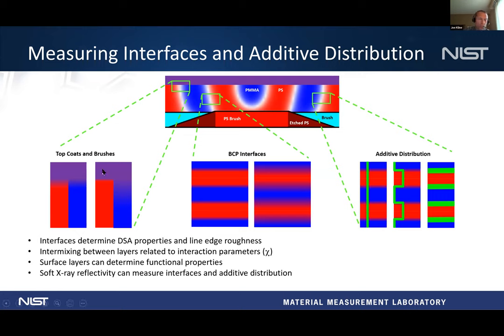And so I'm going to talk today about some top coat work that we did with Grant Wilson's group, where we're looking at how much the top coat mixes with the polymers underneath it. But you can also look at the interface sharpness, which we have a number of papers on. Or if you have a third component or an additive, you can do the reflectivity measurement and see where in the material the additive goes, as long as you have chemical bonds that are different between the three materials.